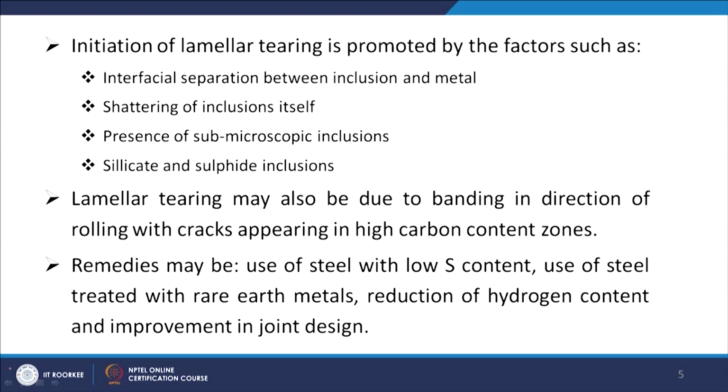Now, if you talk about the factors responsible for the initiation of lamellar tearing, the initiation is promoted by many factors, and among them one is the interfacial separation between the inclusion and the metal.